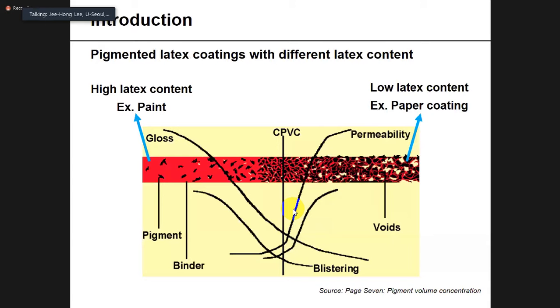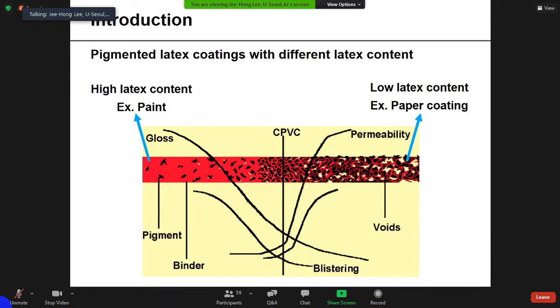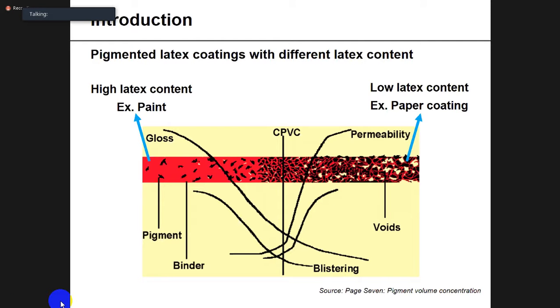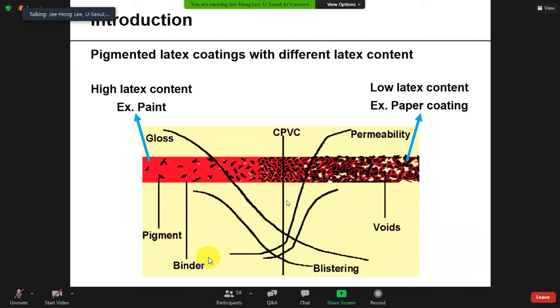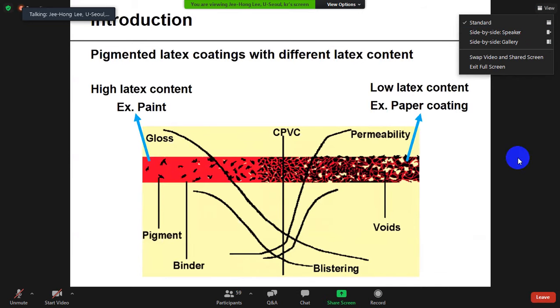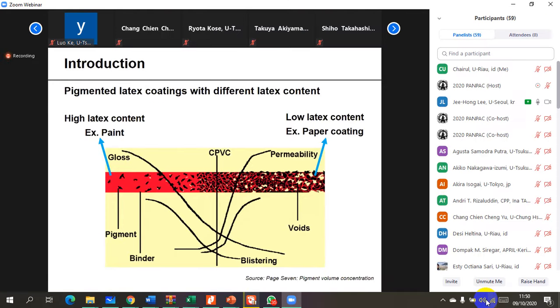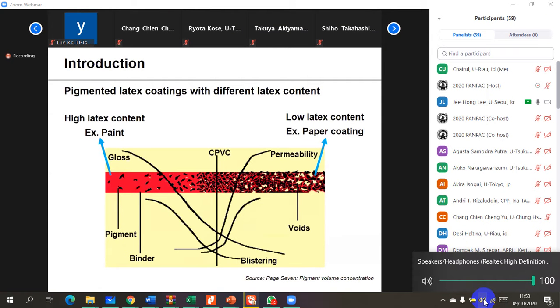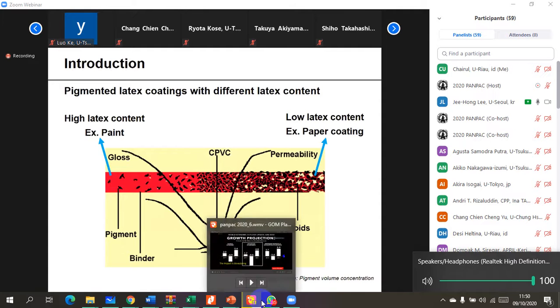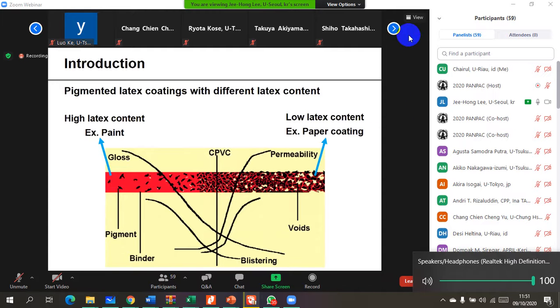The structure of these pigmented latex coatings would be quite different depending on the latex content. If you have a high latex content, like paint, then the latex binder makes a continuous film and the pigments are inside of the film. However, when the latex content is low, for example in paper coating, voids are introduced into the structure and the latex film doesn't become continuous anymore.